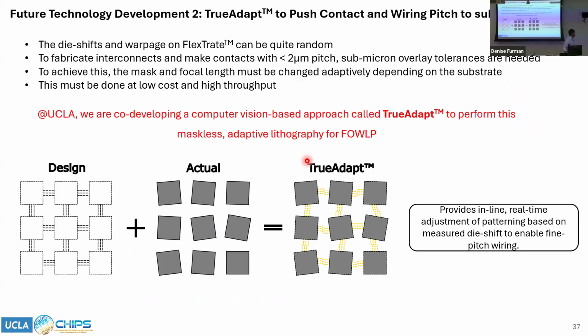So what TrueAdapt actually is, it's a new way to do lithography, wherein, imagine you originally had this kind of layout of connecting the dies, but then after you put it inside your molding compound and cured it, the dies are shifted in position. But what TrueAdapt can do is it uses basically a microscope to map out the surface of the wafer, and this is done automatically and at very high throughput. And once the surface is mapped, it then regenerates a layout, and then this regenerated layout is used in a maskless lithography tool to print the interconnects to connect the dies together. So irrespective of how the surface is modified, you can use this kind of approach, basically a computer vision based approach, to modify your interconnects so that the dies still end up getting connected.